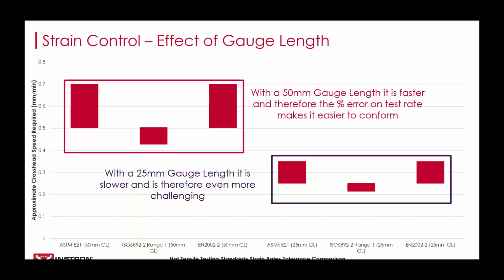So we just looked at how crosshead speeds vary between ambient and elevated temperature tests. Now let's consider the effect that gauge length has. On the left, we see that whether testing in ISO or ASTM, there's a much larger window of conforming speeds compared to the tighter range on the right. This highlights the difficulty of testing smaller specimens in strain control at elevated temperatures.